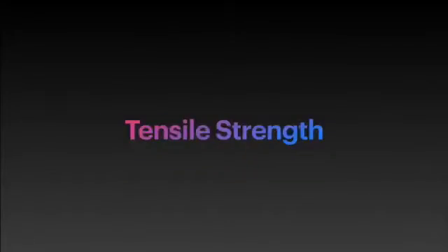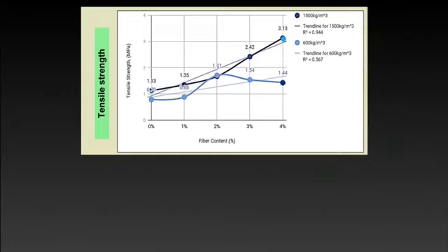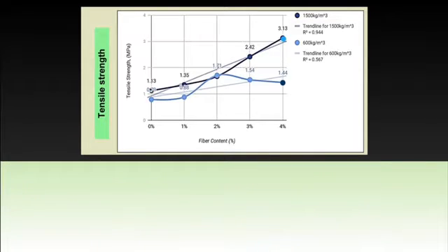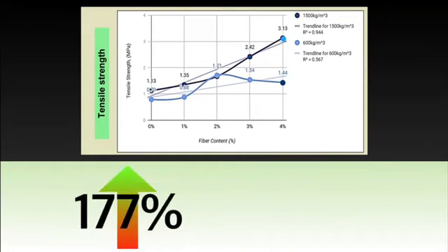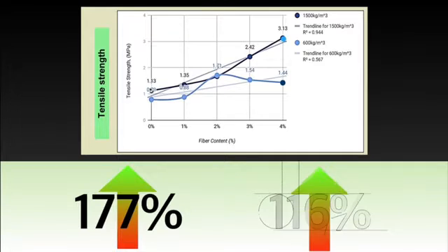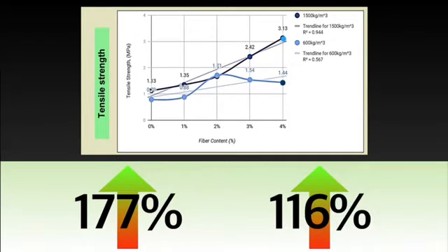Now, for tensile strength. For higher density Pulpcrete, an increment of 177% is observed in terms of tensile strength, while for lower density Pulpcrete, an increment of about 116% was observed when compared to normal non-reinforced foam concrete. This outstanding increment in terms of tensile strength means that Pulpcrete can withstand a lot more pressure than normal non-reinforced foam concrete along the length of the concrete.